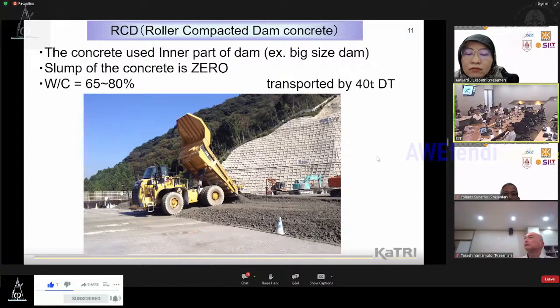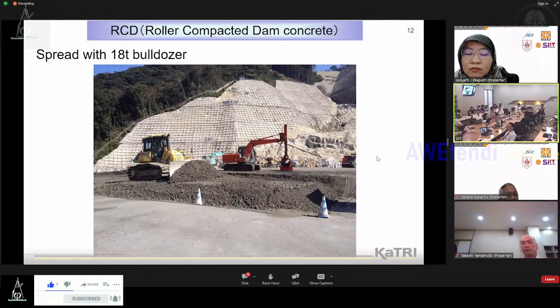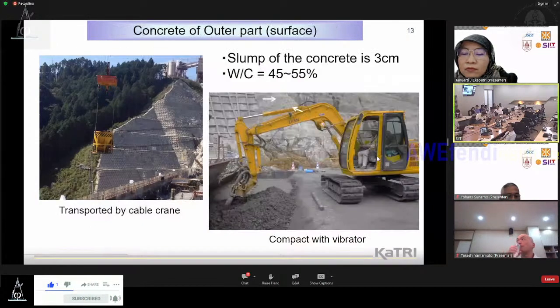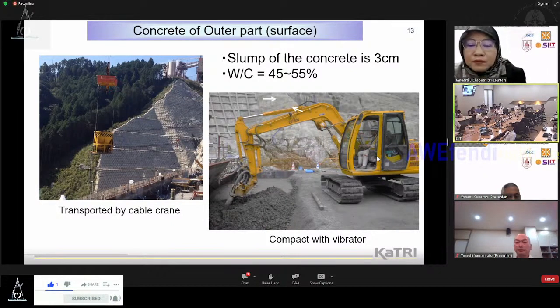So we transport it by dump truck like this, and then spread it with a bulldozer, almost 1 meter height in one layer. So many layers are spread in the dam concrete. At my work site, the dam height is about 100 meters, so 100 layers are spread in the concrete dam. This shows the outer part, the surface area of the concrete. The slump of the concrete is 3 centimeters, and the water cement ratio is almost 45 to 55%. It is transported by cable crane and compacted with a very heavy weight, like in the right photo.